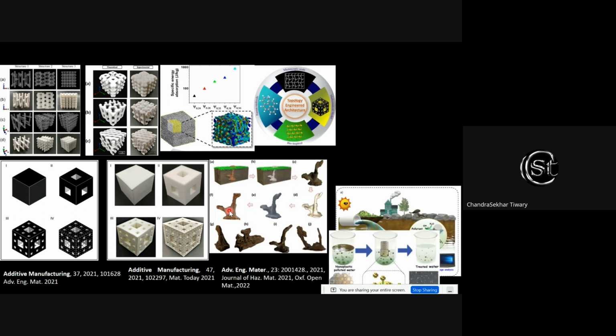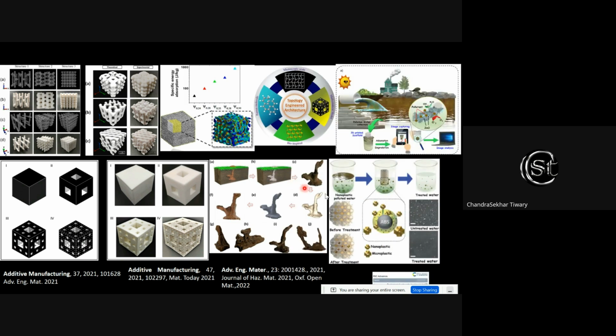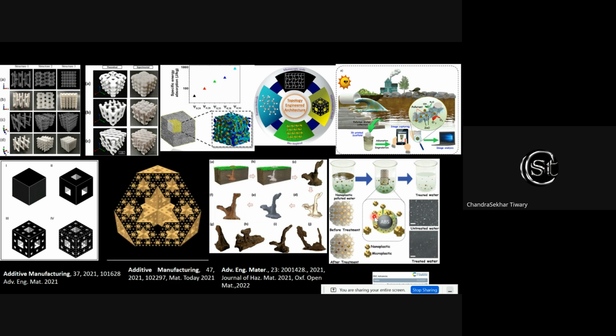And remember, all these structures can be utilized, or we have utilized them already, for water treatment, catalysis, templates, and so on, where we have a high surface area, low density, and reasonably high strength to retain the structure. We utilize this porous structure as a template where we can grow some nanomaterial, for example zinc oxide and so on, which can treat the water. These 3D printed structures are coated with certain chemicals which can absorb nanoplastic or microplastic. So all these 3D printed structures can be utilized in functional or environmental applications.